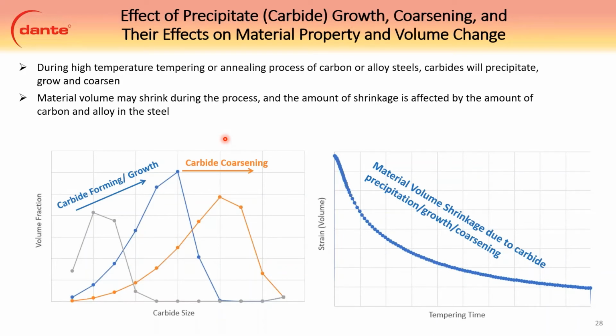And we can also consider the effect of precipitate growth and coarsening and their effect on material properties and volume change. So we describe it as a size function. Your probability of having carbides of this size is essentially what this curve says. As time goes on, you essentially get higher and higher carbon and carbide. The bottom is going to be the carbide size. And you also shrink as your carbides coarsen.